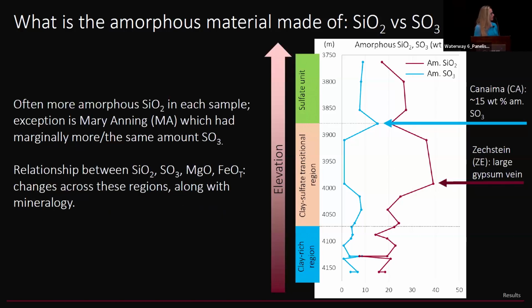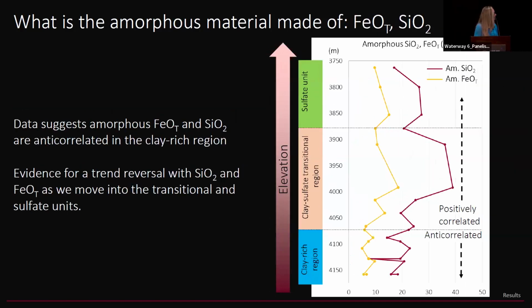Just a couple of notable samples. Canaima had the largest amorphous sulfate component, about 15 weight%, and Zechstein is really hard to work with. Zechstein was a sample we analyzed that was a really big chunky gypsum vein, and it's usually an outlier in almost all of my data sets, so I try to ignore it for the most part. And the relationship between the SiO2, SO3, magnesium, and iron does change across these regions along with the mineralogy.